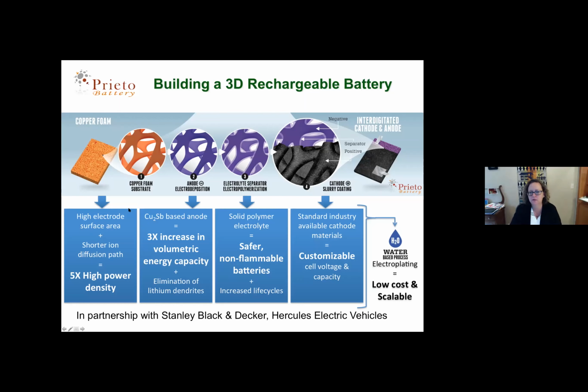This we buy by the roll, and then we just punch out the shape that we need for the battery that we're trying to build. Copper is a very common current collector for the anode side of a lithium-ion battery anyway, but it's a really good working electrode. The surface area to volume of that foam sets the theoretical maximum for the power density of the battery. So in theory, this battery should charge and discharge 5 times faster than a 2-dimensional battery made of the same material. We use that as a working electrode, and then we electrodeposit our anode.